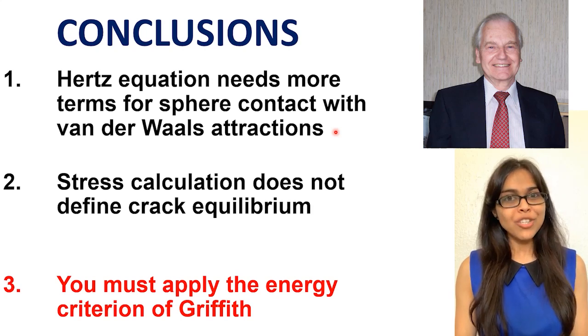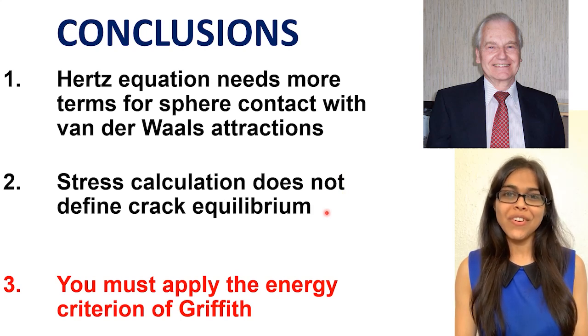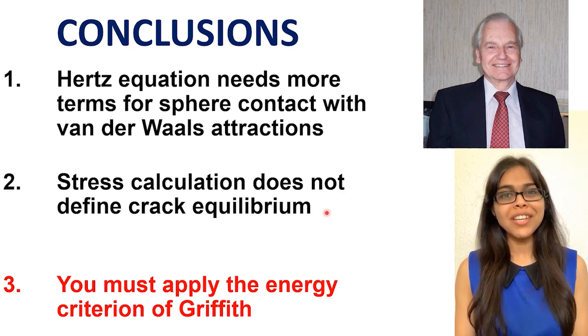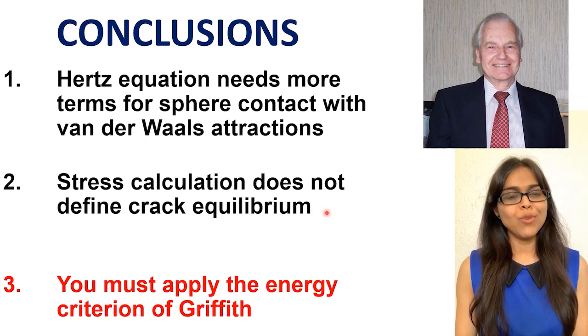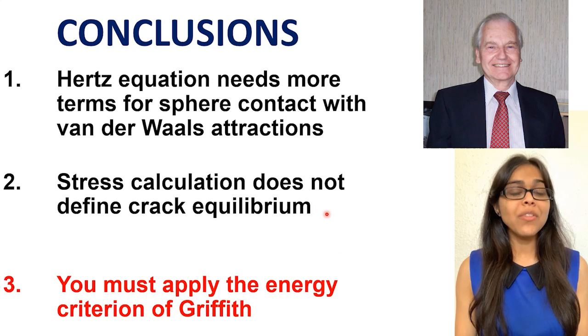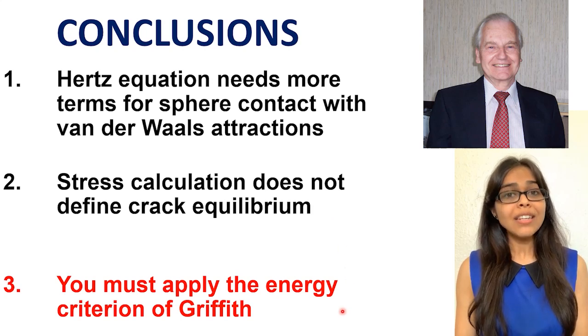This story shows that stress analysis in itself cannot give the condition for cracking. Stress theoretically goes to infinity at the crack tip. The stress distribution must be used to work out the energy balance argument that Griffith invented in 1920.